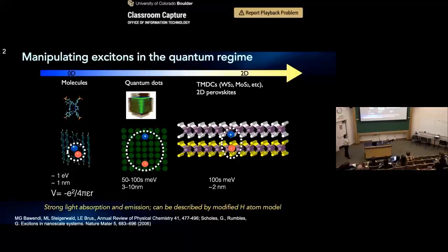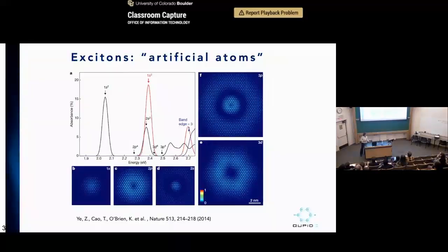The special thing about these two-dimensional semiconductors is that they are single or few atoms thick, so that while the screening epsilon is very large in plane, out of plane is vacuum, so it's very weak screening. So you would have very strongly bound excitons as well, and they depend highly on how you layer them. The dielectric environment can strongly affect how these excitons behave, and so these excitons are going to be our quantum particle of choice, and the question is how we can manipulate them, and in particular their interaction in these solid-state systems.